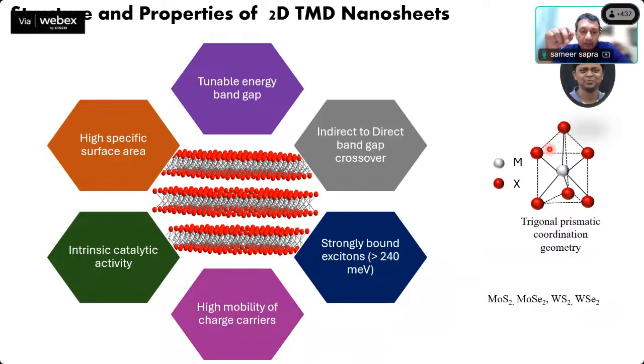If you have just two electrons, then rather than the octahedral coordination, the trigonal prismatic is more favored, because in the trigonal prismatic, the crystal field effect is such that you have two orbitals at the bottom, then one, then one, and then one. So these two orbitals at the bottom are occupied. The third electron is not there. But if you wanted to put a third electron in a trigonal prismatic, it would go to a higher energy level. And therefore, when you put a third electron, it crosses over and makes an octahedral coordination.